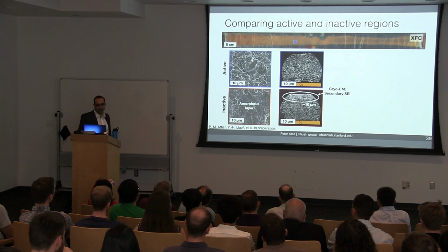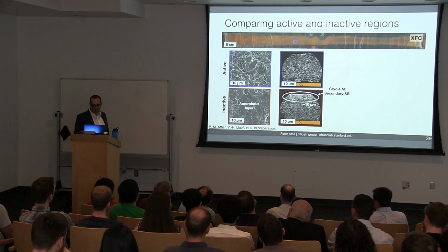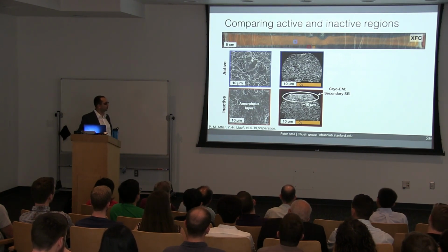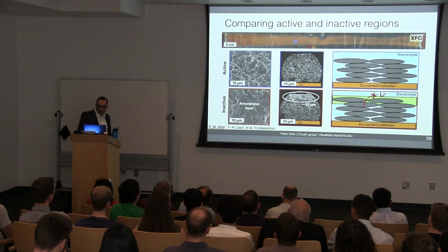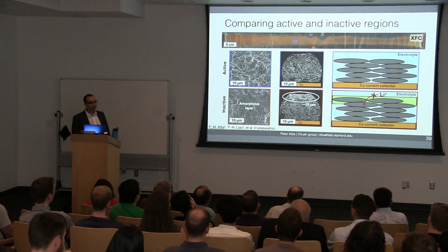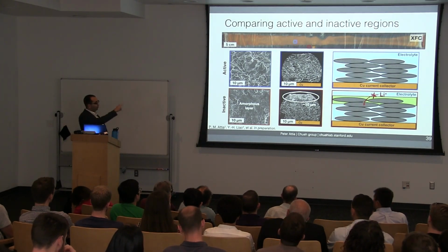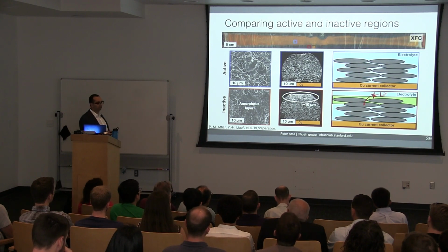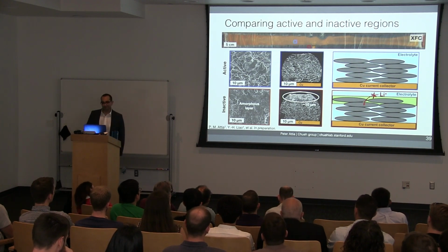And I'll briefly mention that we also did Cryo-EM of the surface and found that it contains some sort of electrolyte components. So it's possible that this electrolyte component was originally some sort of lithium metal, but when we measure it, it's basically just SEI. So what we can conclude is that the surface layer is likely blocking lithium ions from entering the bulk of the electrode. And this is what's responsible for the widespread electrode deactivation.